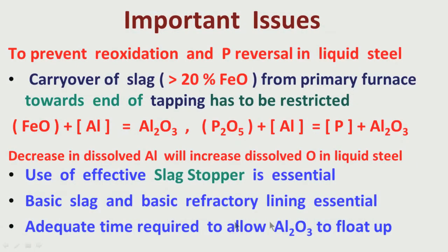This is very important. I have told you the basic slag and basic refractory are essential. Because why? If you don't have basic refractory, meaning refractory rich in CaO, and you have some amount of SiO2 in the refractory lining, then this SiO2 will again react with aluminum in liquid steel and generate Al2O3. Reoxidation will take place, dissolved aluminum will come down, dissolved oxygen will go up. So this is again a problem.